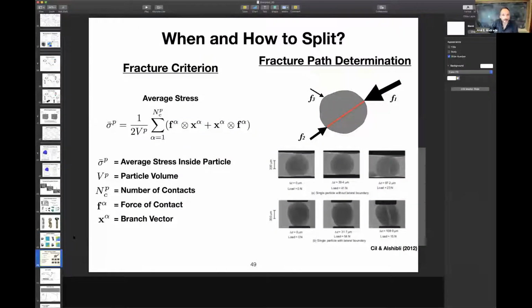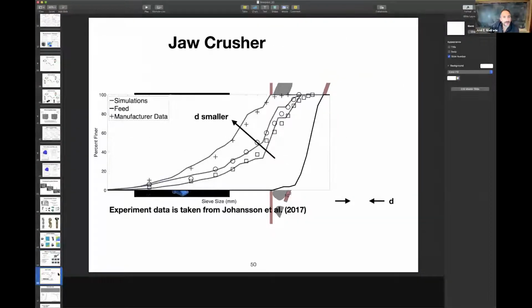So I won't get into the details, but essentially you use the external loading, the forces, to compute the average stress in the particle. You don't have to do that. That's how we choose to do it to make it faster. And then using that average stress in the particle, we're able to split our particles. And we get remarkable similarities with experiments.